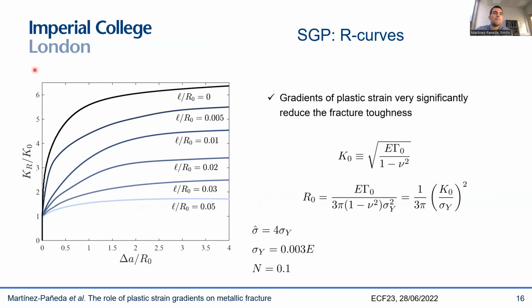So this is the stress intensity factor, a measure of the crack tip stresses of the applied load, versus the crack extension, normalized by this R0. And you can see that depending on the value of the length scale, you go from this very significant plastic dissipation in the case of conventional plasticity, and this agrees with those results by Tvergaard and Hutchinson. But then as we increase this ratio of L divided by R0, we see a very significant degradation of the fracture resistance, basically. You have much higher stresses, and therefore you lower your fracture resistance.